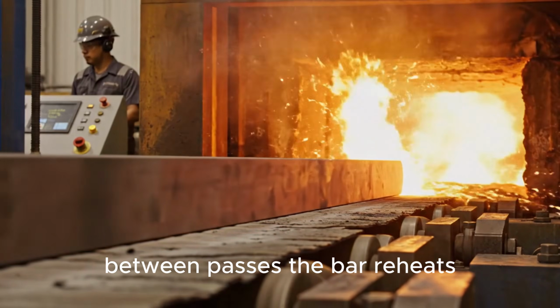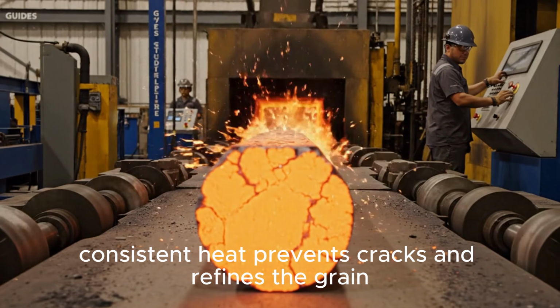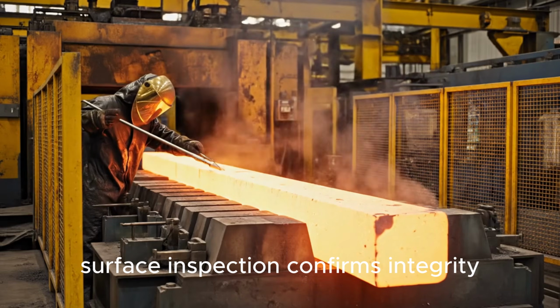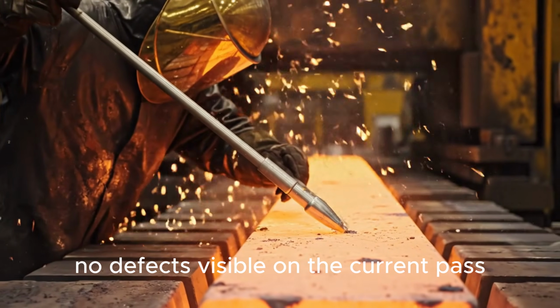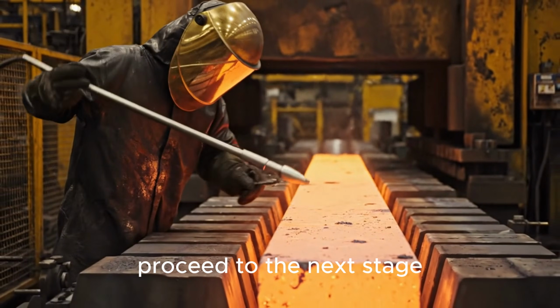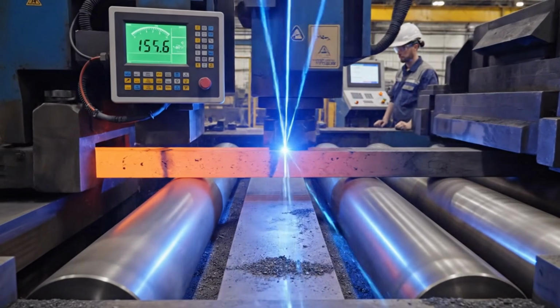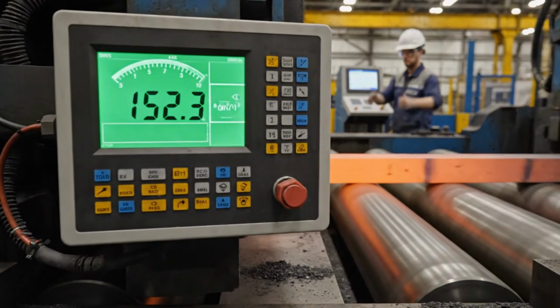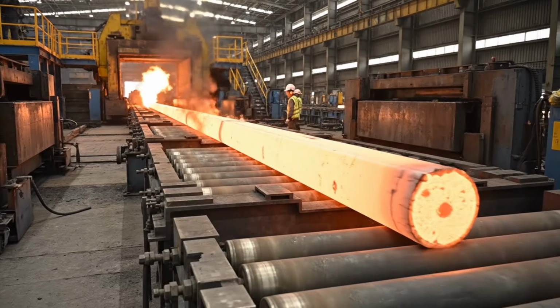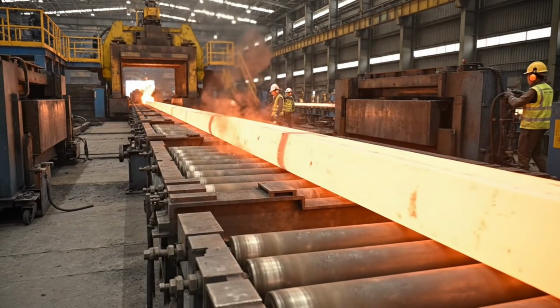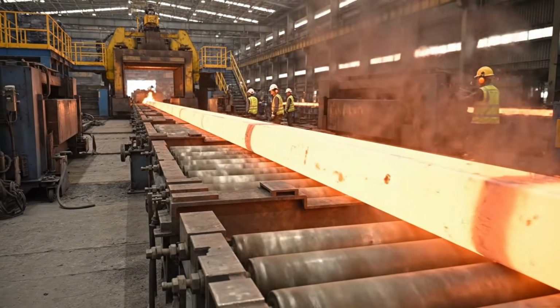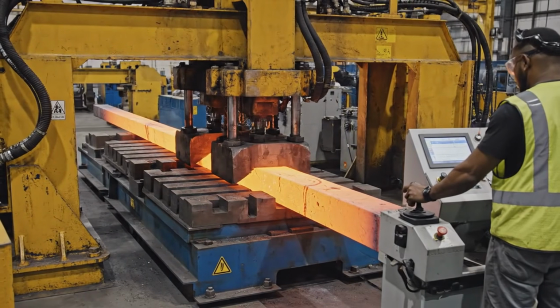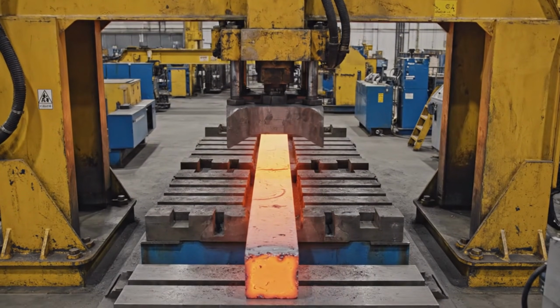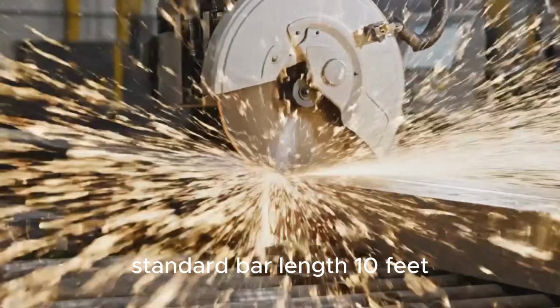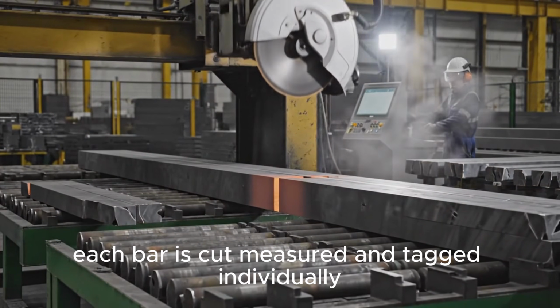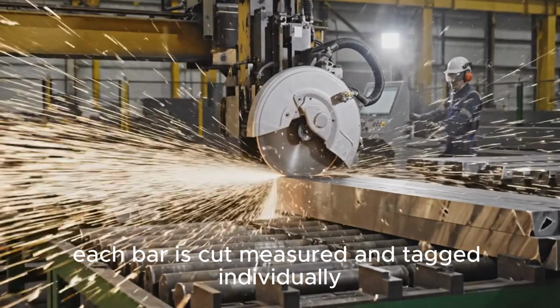Between passes, the bar reheats. Consistent heat prevents cracks and refines the grain. Surface inspection confirms integrity. No defects visible on the current pass. Proceed to the next stage. Standard bar length, 10 feet. Each bar is cut, measured, and tagged individually.